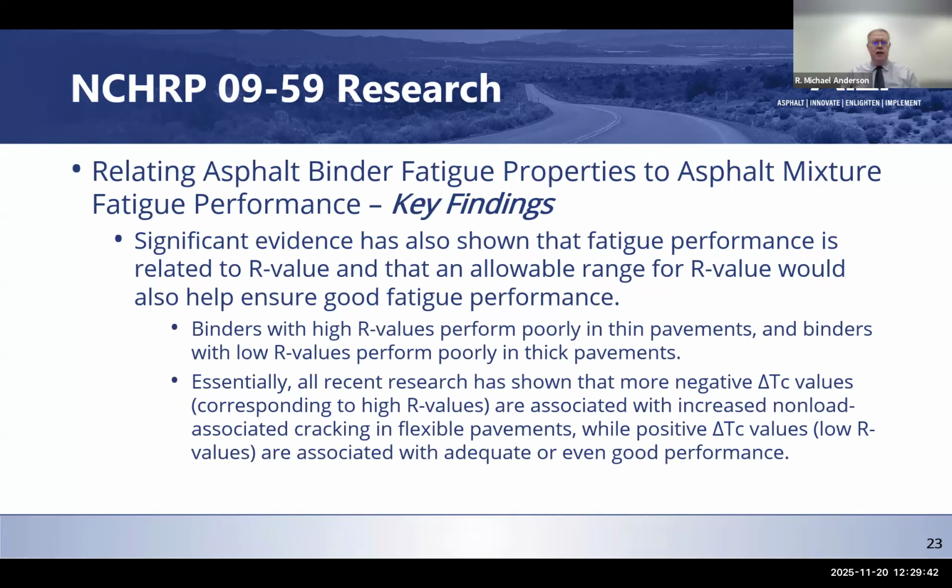Another key finding that they had was that there is significant evidence that suggests fatigue performance is related to R value, and an allowable range of R value would also help to ensure good fatigue performance. What they've found was that binders with really high R values perform poorly in thin pavements, and binders with low R values tend to perform poorly in thicker pavements.